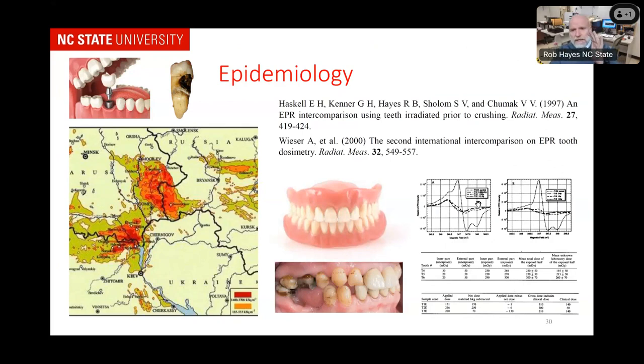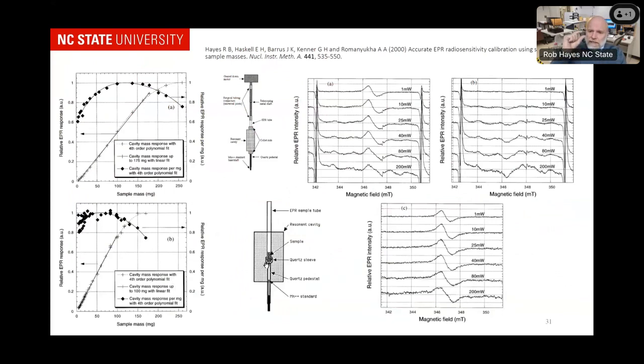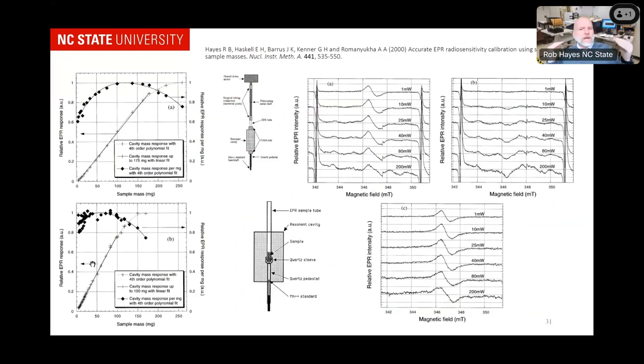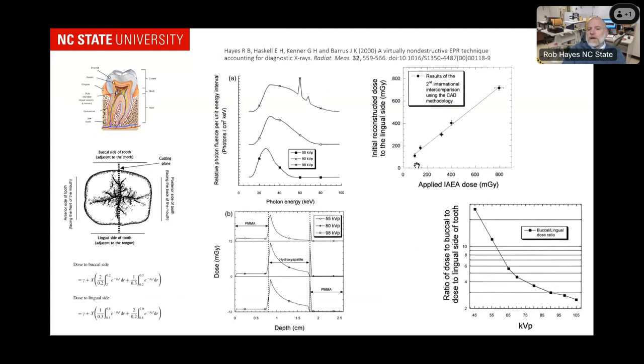We published a lot of work using epidemiology — looking at dosimetric and native signals, you can not only use it for forensics but also epidemiology. I also published that as I change the sample size, the signal intensity isn't completely linear with mass because the microwave field has a cosine distribution and there's dielectric focusing from the electric component. Even with Helmholtz coils, there's still some curvature. Another paper shows how you can discriminate against energy — if I want to figure out the energy from dental X-rays, I know there was attenuation through the tooth, and I can calculate that to reconstruct the dose. The energy deposition gets high once you're in the tooth, then back low in the soft tissue.